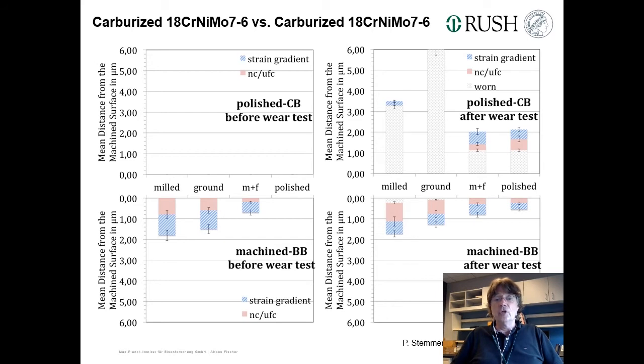From the polished base body here, we found tribological material and we found a strain gradient, meaning this has been generated under the tribological test, as it has been in the counterbody. But the counterbody brought about most of the wear in the whole system, while these two showed ultramild sliding wear. So this didn't really matter. Certainly people say that the counterbody always wears more than the base body, but again, that rule is not really true. It could be exactly the other way around.